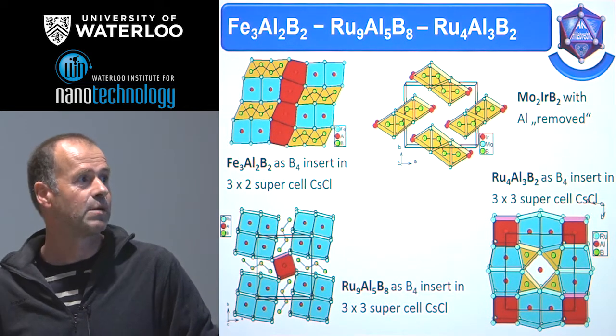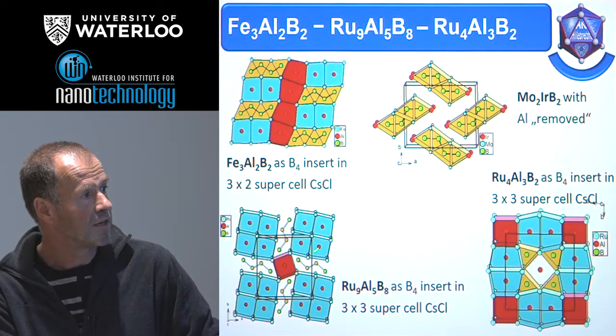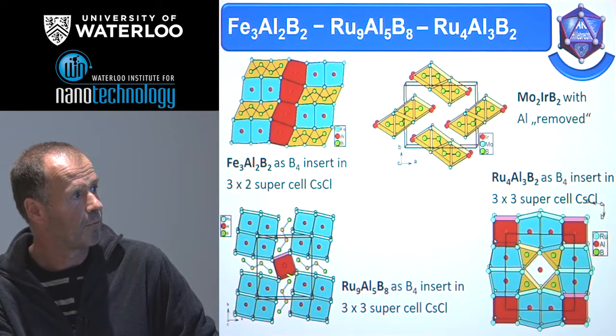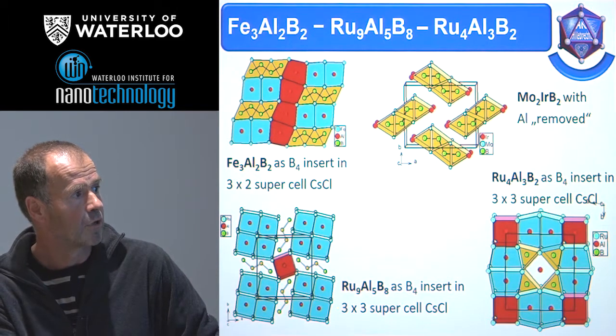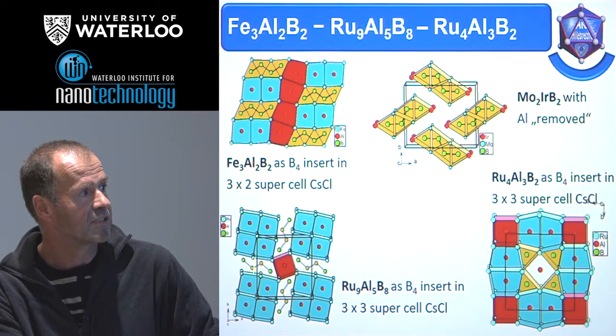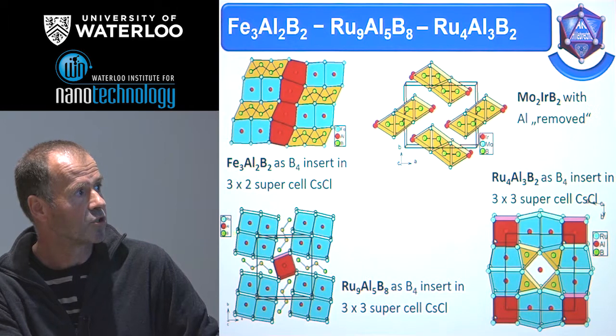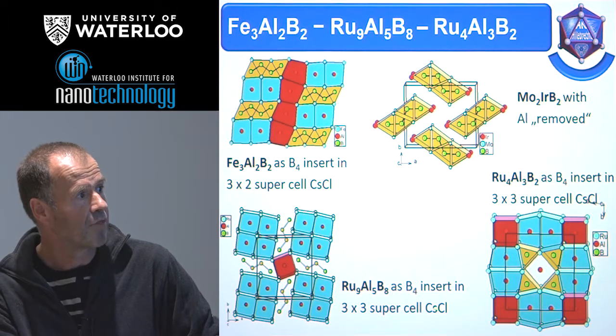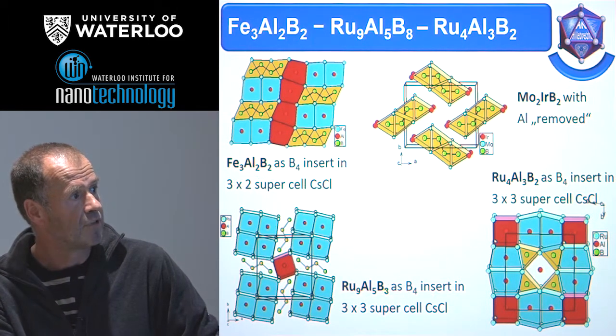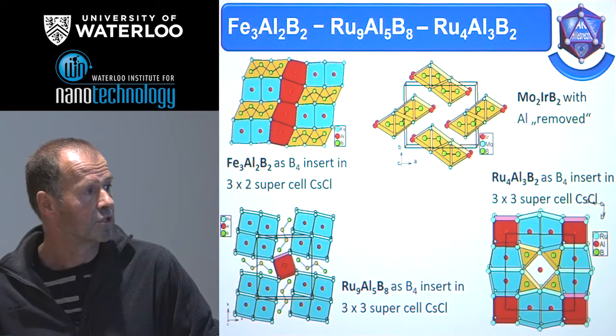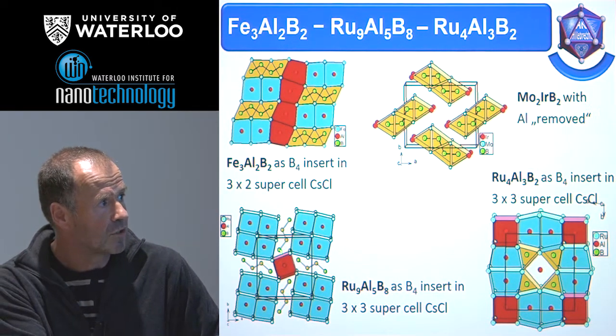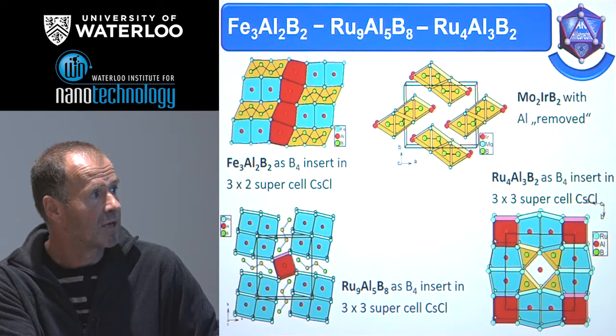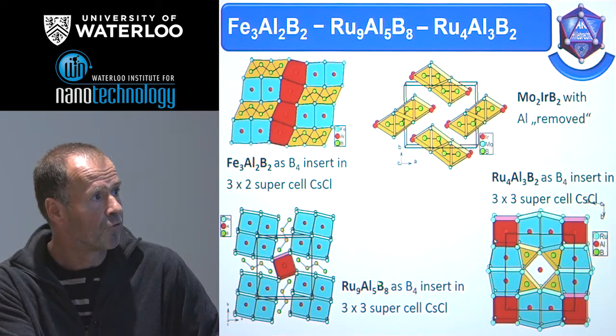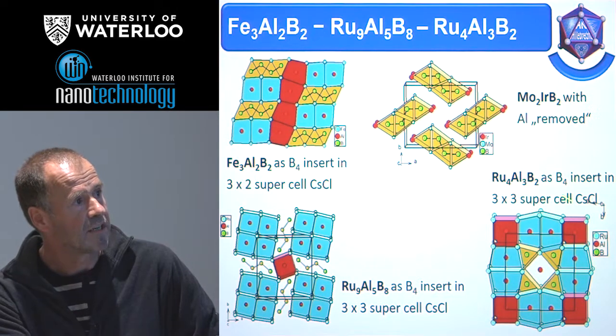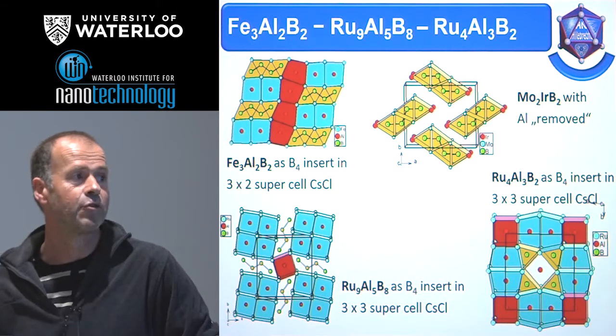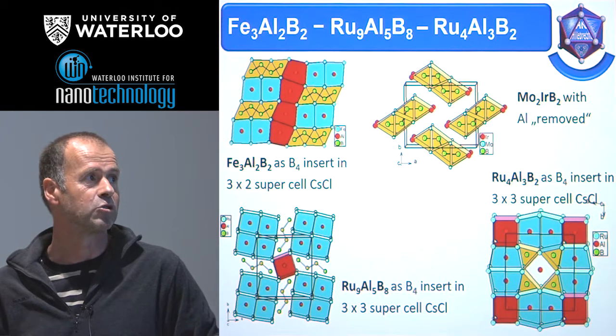it works quite well. And for some of our new compounds we have found, for example, this ruthenium compound is just an example for a 3×3 supercell. Now you have a larger share of the intermetallic part. That's quite clear because you have a different connection of the transition metal part, because you have a higher share of the boron. And this continues a series that is known from other ternary transition metal borides.